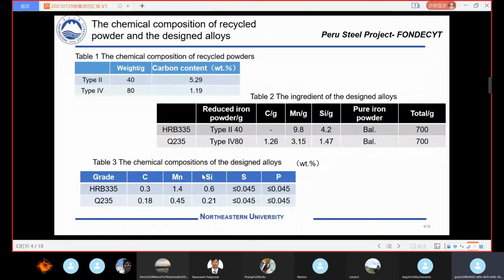Then we talk about the chemical composition of the recycled powder and the designed alloys. Table 1 is the chemical compositions of the recycled powders. There are two kinds of powders, type 2 and type 4, and here the weights are 40 gram and 80 gram respectively. We can notice that the carbon contents in the type 2 and type 4 are different. The carbon content in the type 2 is more than that in the type 4.